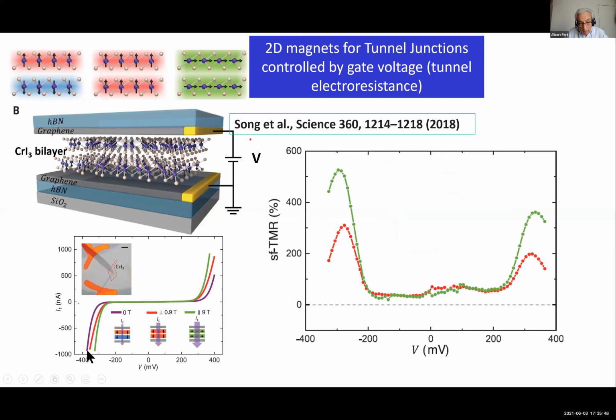So this is a sort of magnetoresistance induced, but this time not by a magnetic field, but by electric voltage between the electrodes, which is, of course, more convenient than applying a field with a magnet, with an electromagnet, for example. So this is very interesting, having the possibility of TMR with only manipulation by electric field. This is, for example, the TMR that is obtained as a function of the voltage applied between the electrodes according to this calculation, with a very large magnetoresistance above 400%.